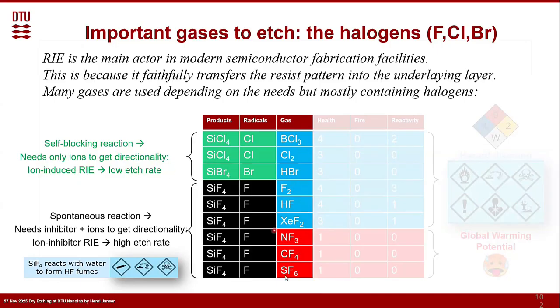The other types are all the fluorine ones, what you see over here, from fluorine up to SF6. They create the fluorine radicals, making the very volatile silicon tetrafluoride product. And this is normally a spontaneous reaction. So it needs an inhibitor like oxygen or C4F8 or CF2 species. And then the ions still have to knock it out to get the directionality. Ion inhibitor reactive ion etching: high etch rate, straight, more difficult to control.